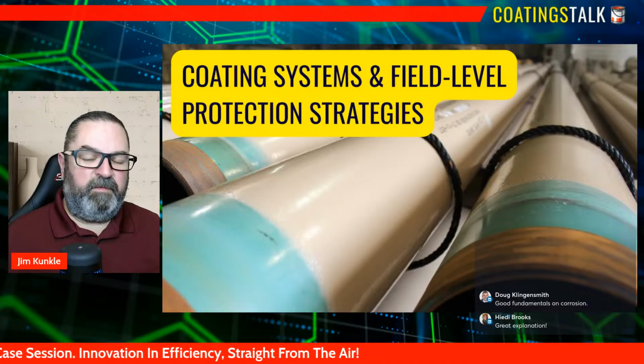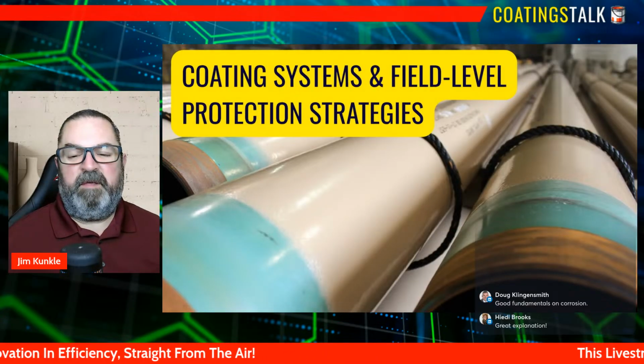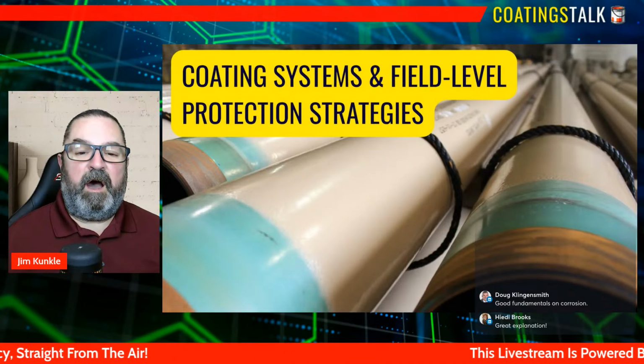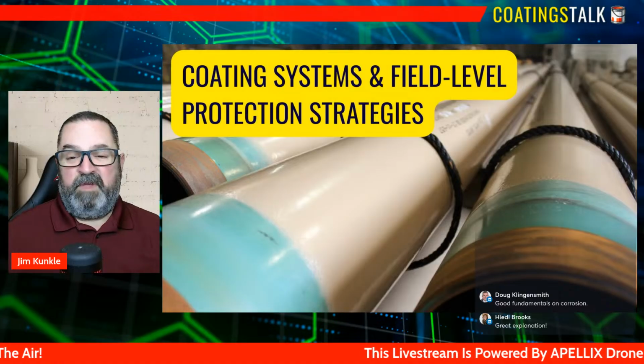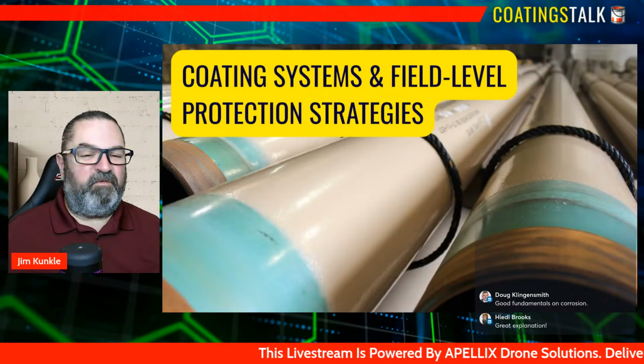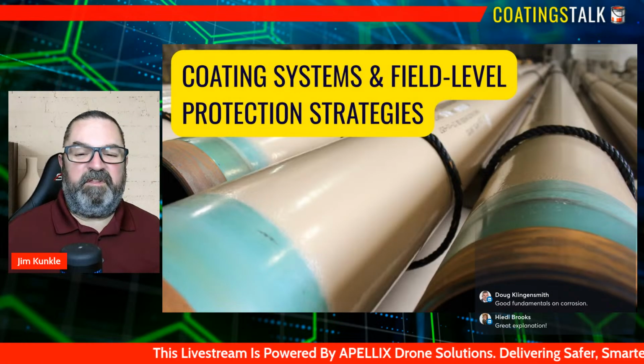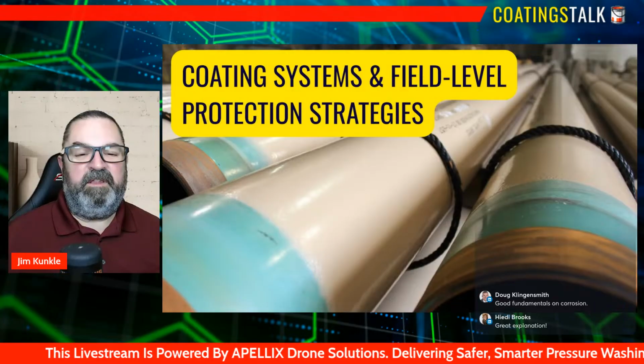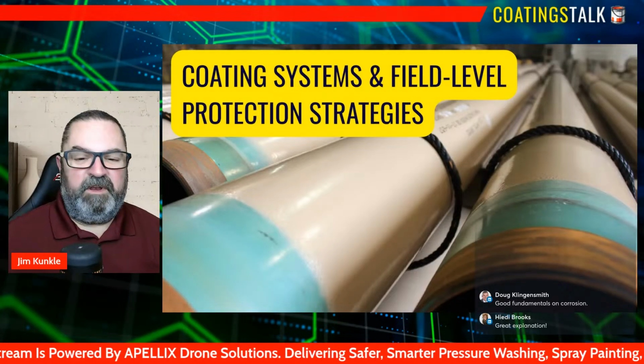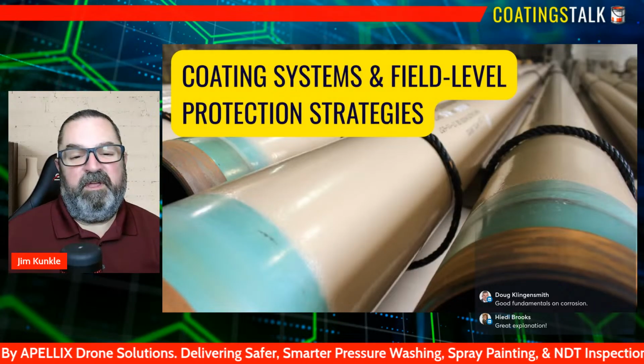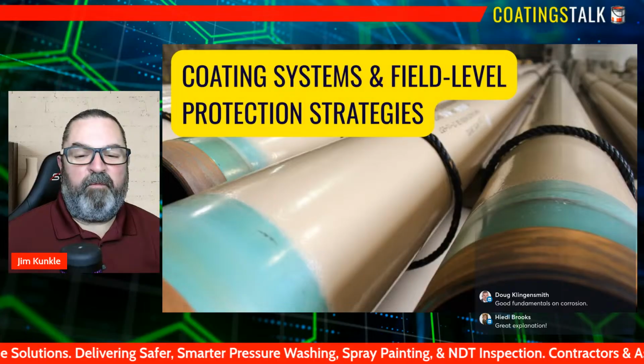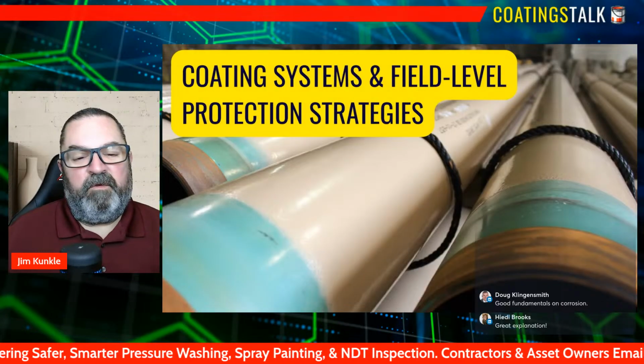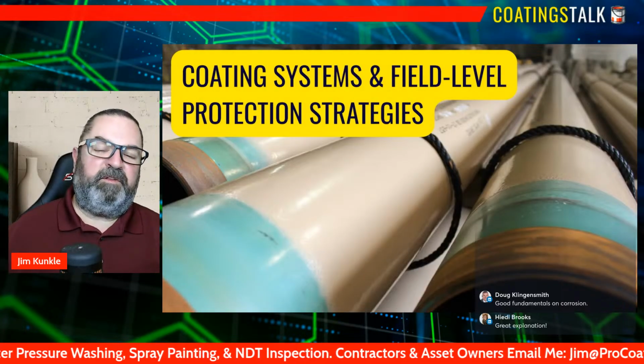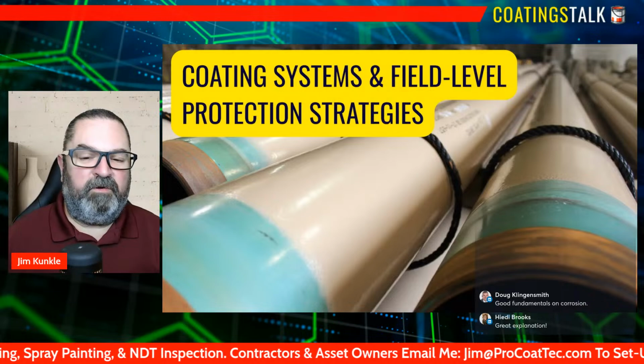Another common mistake is skipping environmental checks. Applying coatings when humidity is too high, temperatures are out of range, or the surface is near the dew point can lead to poor adhesion, solvent entrapment, or incomplete curing. These problems may not show up right away, but they often reveal themselves months later as blistering, peeling, or under-film corrosion.